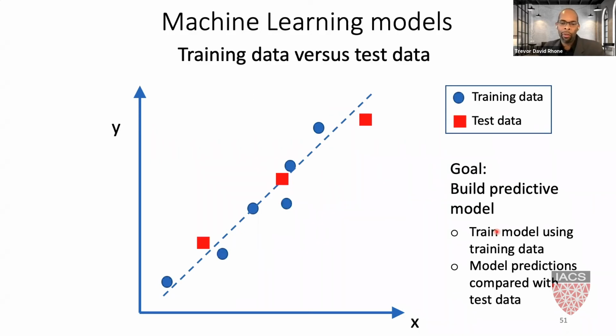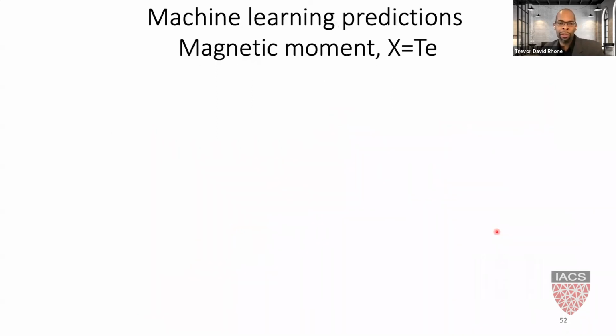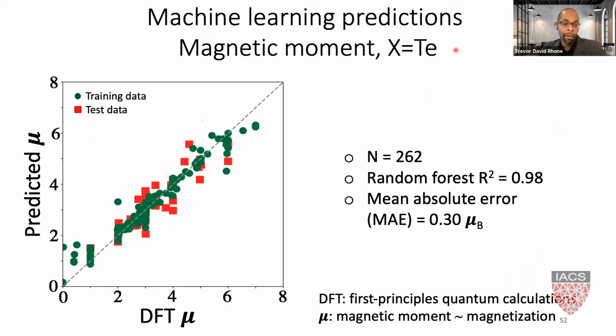Okay, so let's apply this to our data set. Using a random forest, in addition to some other tools, we train a model to predict magnetic moment. And this is the result with the quantum calculations on the horizontal axis compared to the machine learning predictions of the magnetic moment on the vertical axis, with this dashed line being a guide to the eye, representing the perfect prediction line, with the circles being training data and the squares being test data. Now all the points fall reasonably close to the perfect prediction line, indicating that the model is performing pretty well. So we're pretty happy with this model.